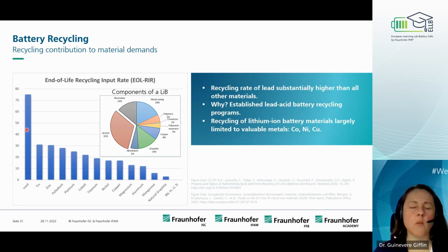So you might ask why this is the case. But it's because there are very well established lead acid battery recycling programs. Of course, in the case of lead, this has to do with the toxicity of lead and ways to keep lead from going into the environment that initially got these programs to be established. But it has basically ended up with a more or less, I mean, not completely, but more or less a closed loop where the resources that are needed are coming from recycling. At the moment, the lithium-ion battery materials that are coming from recycling are largely limited to the valuable metals, so things like cobalt, nickel, and copper. As a comparison, I've put a graphic here of the different components of a lithium-ion battery and what percentage they make to kind of allow you to compare to what could come from the end-of-life recycling input rate.